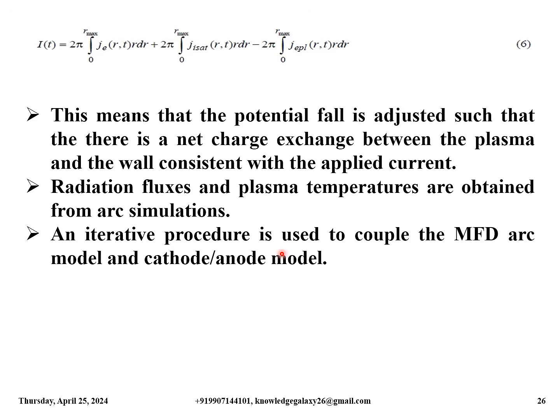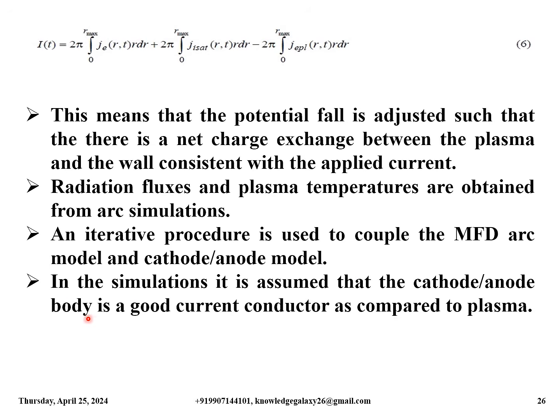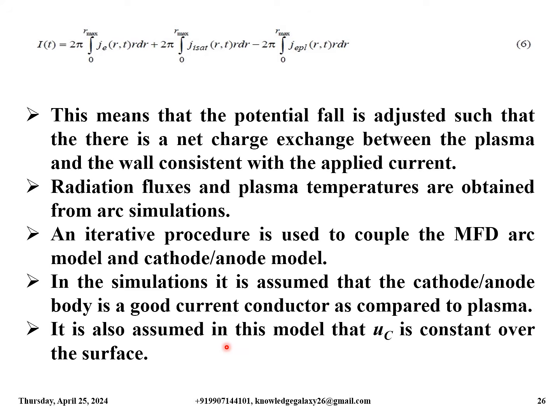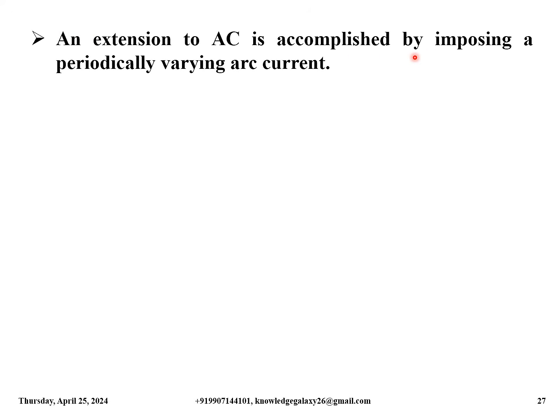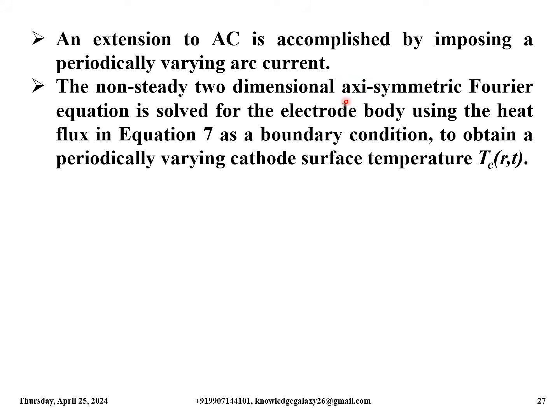An iterative procedure is used to couple the MFD arc model and cathode anode model. In the simulations, it is assumed that the cathode anode body is a good current conductor as compared to plasma. It is also assumed in this model that UC is constant over the surface. An extension to AC is accomplished by imposing a periodically varying arc current. The non-steady two-dimensional axisymmetric Fourier equation is solved for the electrode body using the heat flux in equation 7 as a boundary condition to obtain a periodically varying cathode surface temperature, that is TC(r,t).